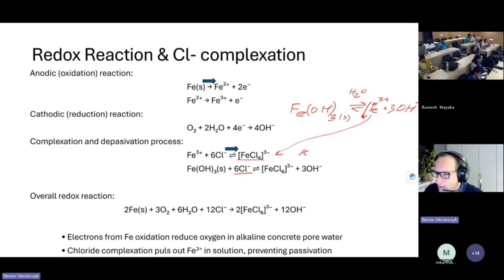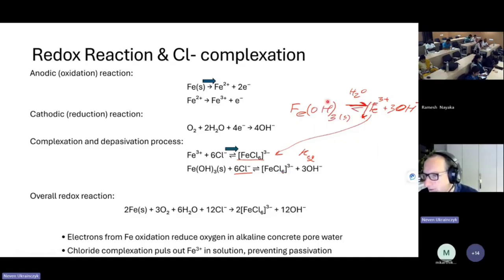We have the equilibrium constant here for the complexation, so it's taking some iron away. In equilibrium you have less iron here, and because you have less iron here, that means you have to dissolve more iron hydroxide, increase the OH actually. So you are making the iron hydroxide more soluble. So either by lowering the pH or increasing the chloride content, that means lowering the iron content here, you are increasing the solubility of iron hydroxide.